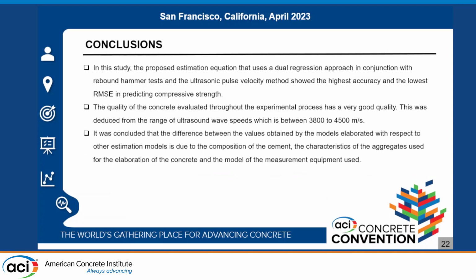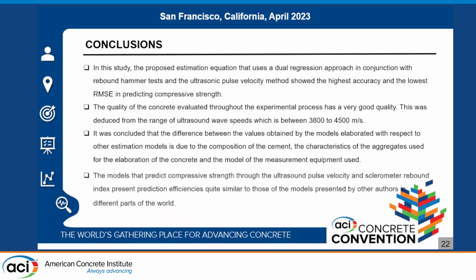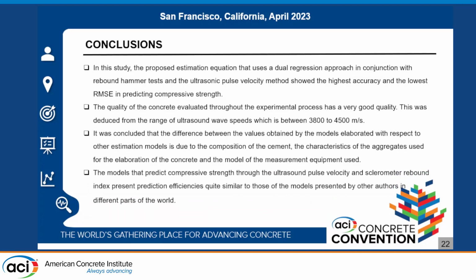It was concluded that the difference between the values obtained by the models elaborated with respect to the other estimation models is due to the composition of cement, the characteristics of aggregates used for the elaboration of concrete, and the model of measurement equipment used. The models that predict compressive strength through the ultrasonic pulse velocity and sclerometer rebound index present prediction efficiency quite similar to those of the models presented by other authors in different parts of the world.